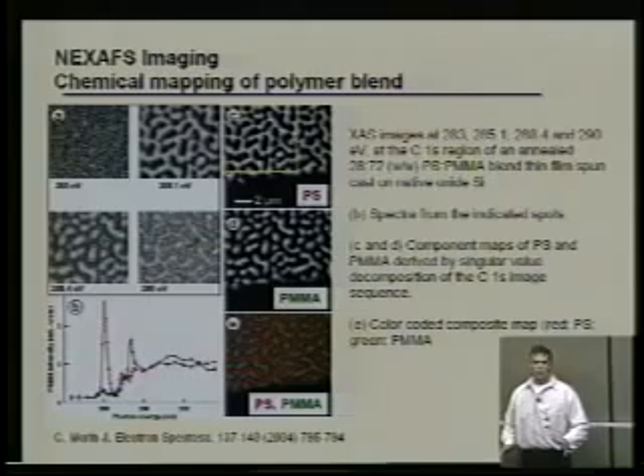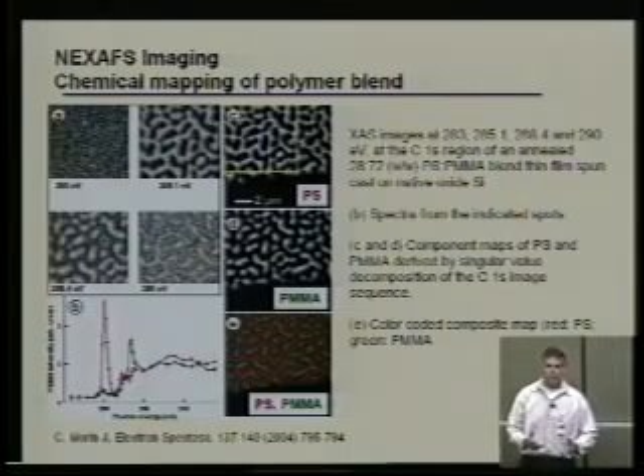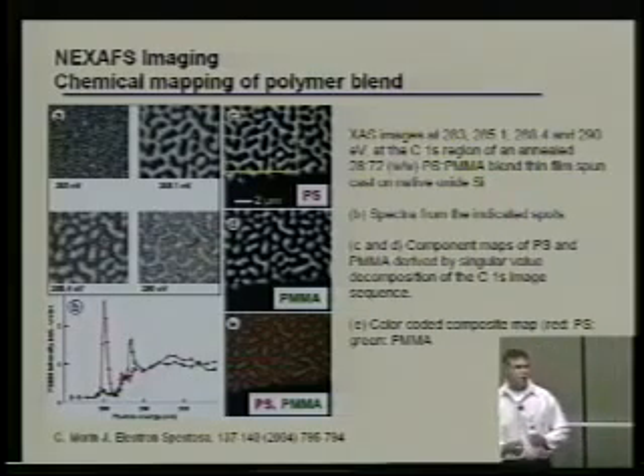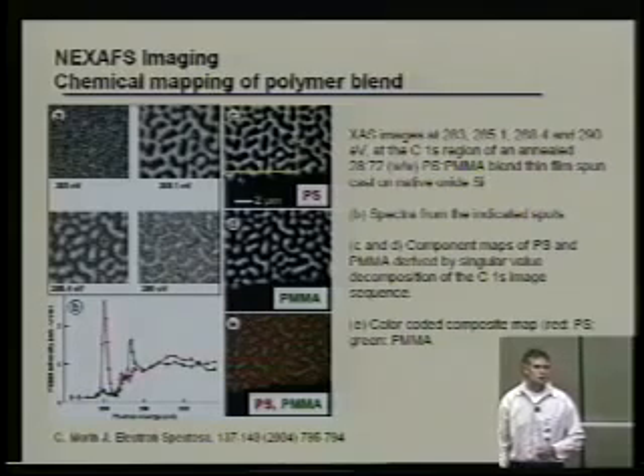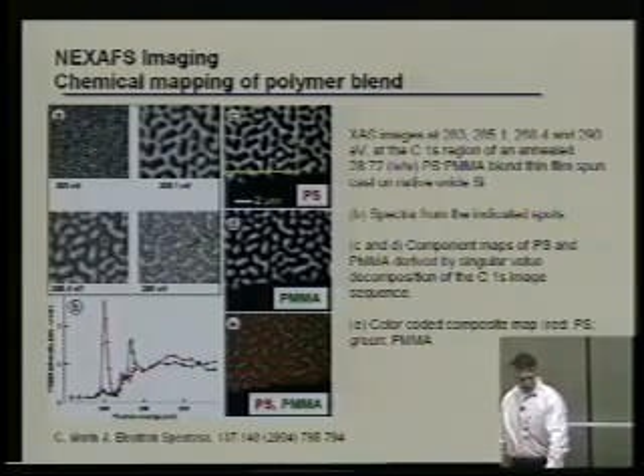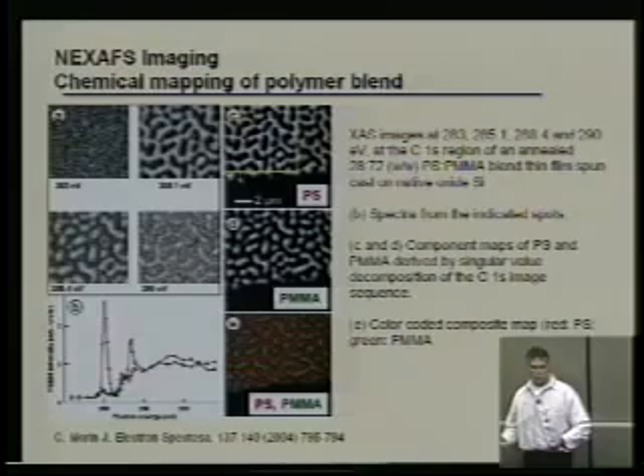So this is a nice way where if you've got polymer blends that have different absorption edges, you can look at your sample and actually see segregation in these materials as a function of processing. And there's a nice plot in section E that's color that shows you exactly how these materials separate.